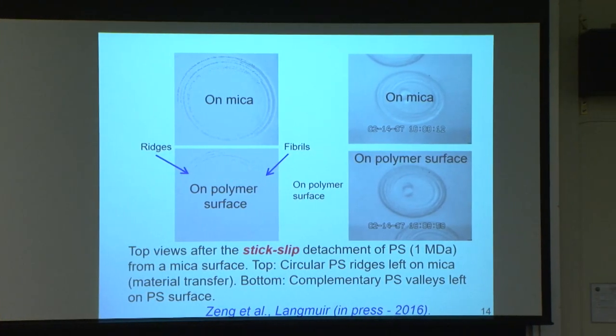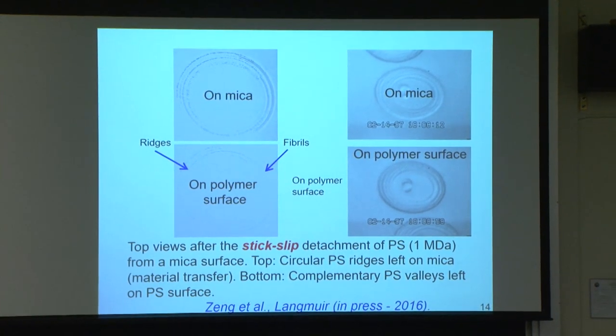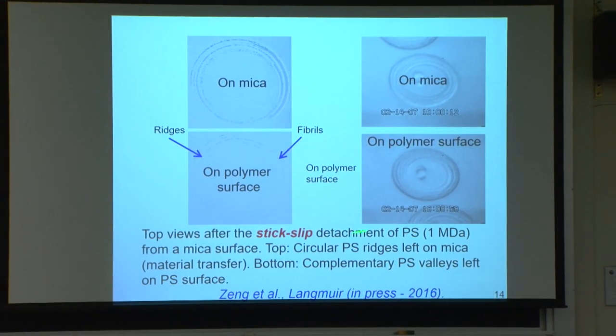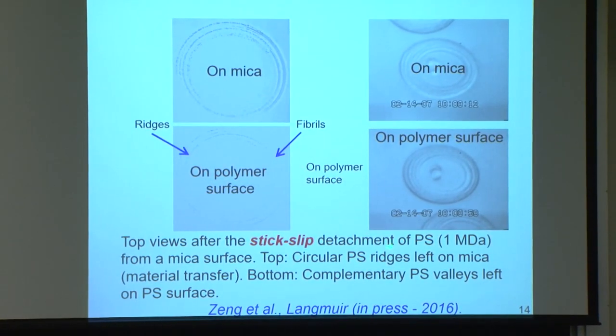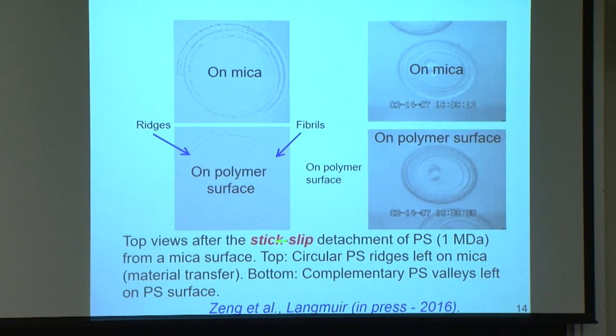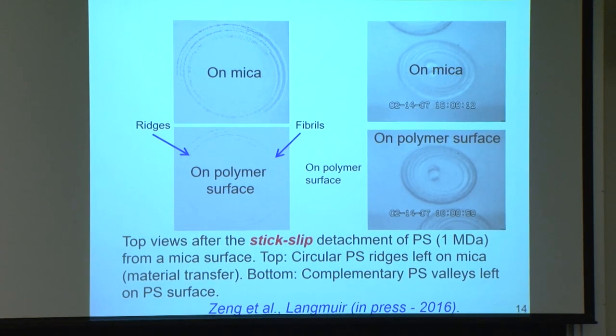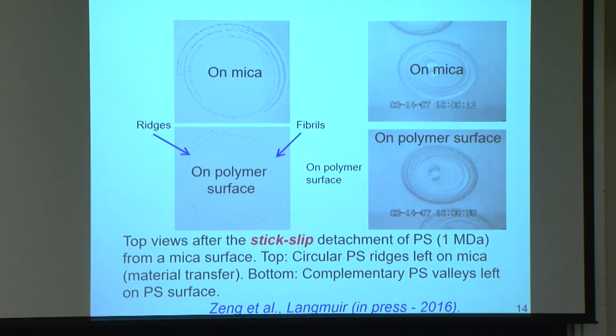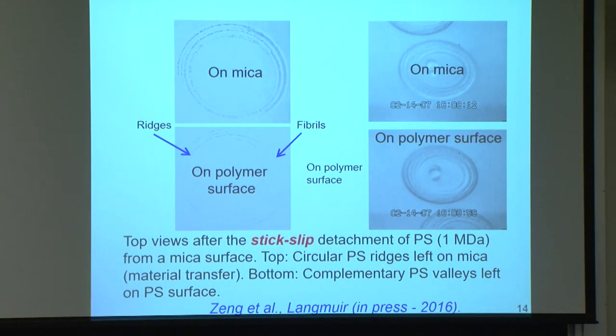An example of this in a non-biological system is what happens when two surfaces, in this case a polystyrene surface, are brought together against a mica surface and just left for a long time. And this polystyrene is not cross-linked. So what happens on separating is, interestingly, that what's left behind on the mica is rings of polymer that have been transferred to that surface.